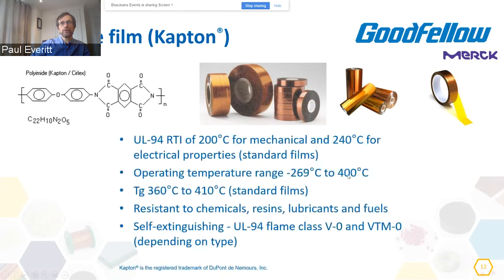If we move on, we'll see that you've got a UL94 RTI of 200 degrees C for mechanical and 240 for electrical. So you're looking at a really robust material that can operate across a very broad temperature range, which goes from the cryogenic, minus 269 degrees C, to 400, which very few materials could offer while staying flexible. The key temperature characteristic, we talked about glass transition temperature, is from 360 to 410 degrees C. That's phenomenally high for a polymer, and is really interesting.